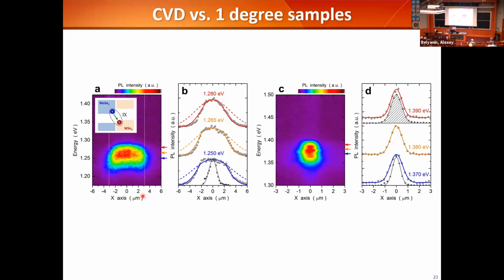So these spectra, I should explain, this is a spatial extension. This is energy. So this is CVD. So I just have a broad blob of interlayer exciton. And this is a stacked sample. I actually have multiple transitions I can distinguish.